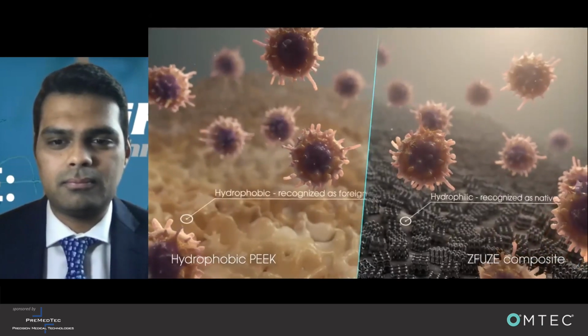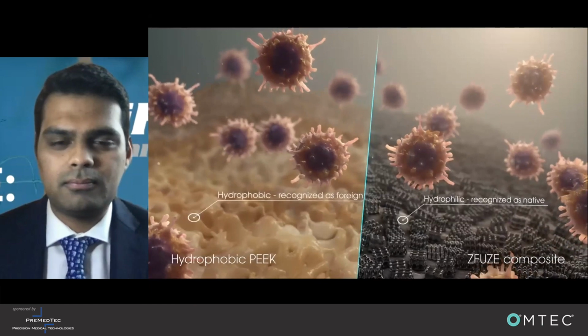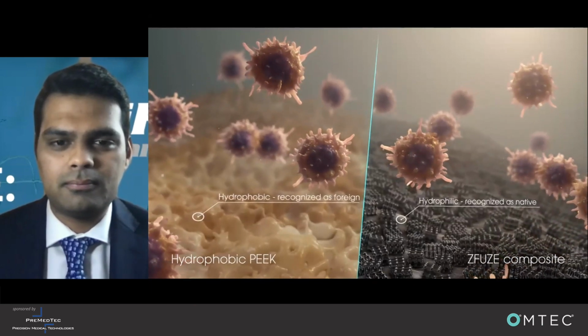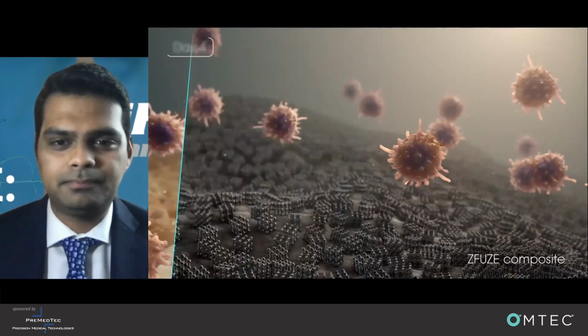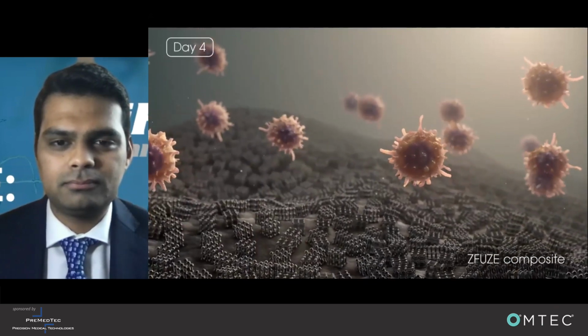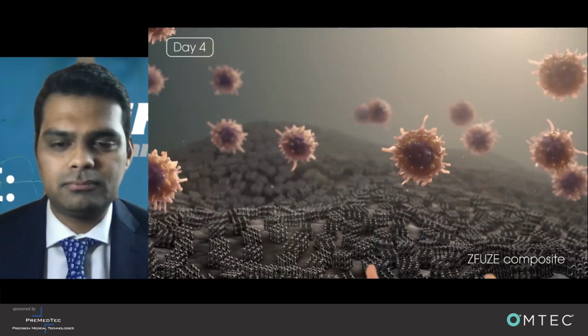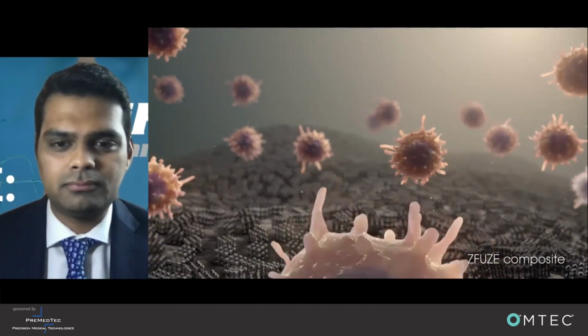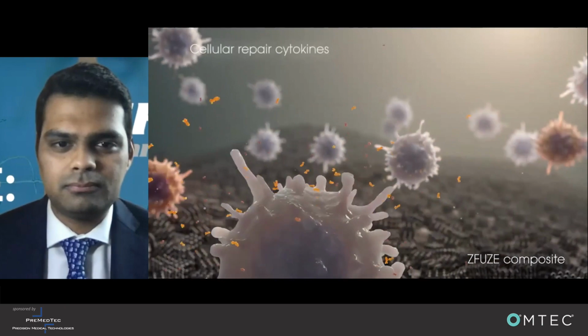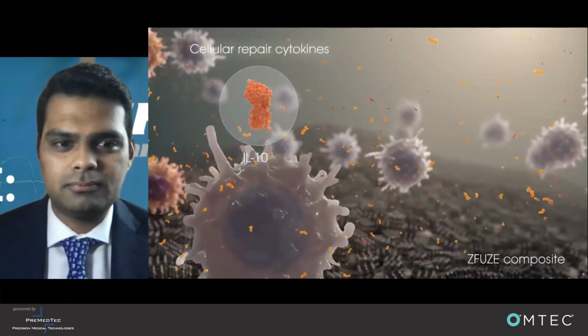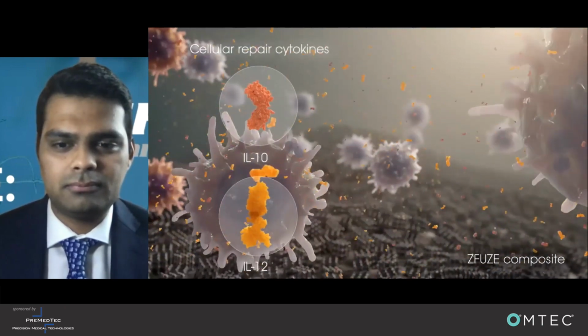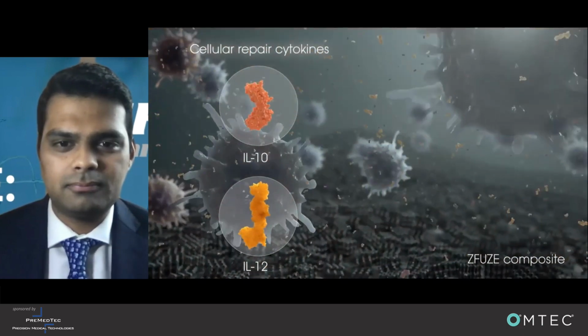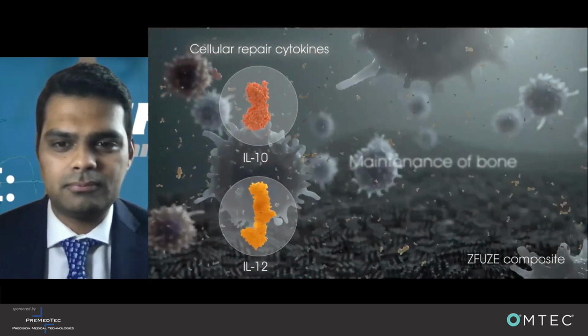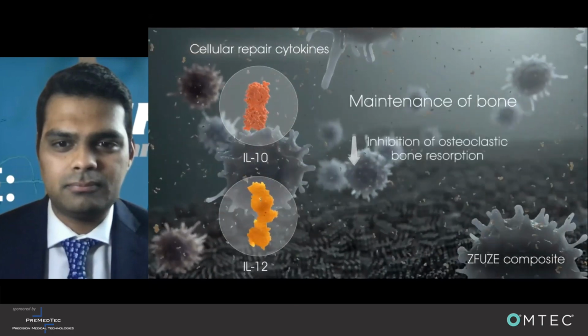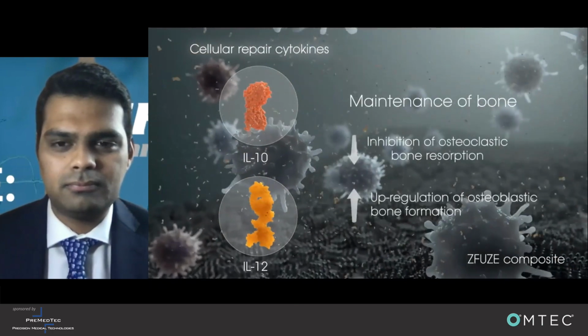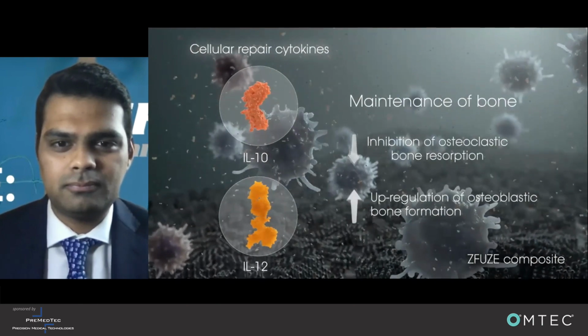The immune system recognizes hydrophobic materials as foreign contamination since native surfaces within the body are hydrophilic. At day 4, a sudden and drastic shift to an M2 phenotype was observed on the ZFUZE surface. The M2 phenotype signals for anti-inflammatory and cellular repair cytokines, such as interleukin 10 and interleukin 12. IL-10 and IL-12 contribute to the maintenance of bone mass through the inhibition of osteoclastic bone resorption and upregulation of osteoblastic bone formation.